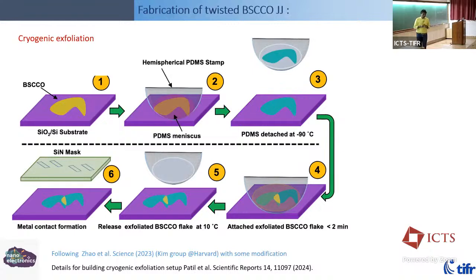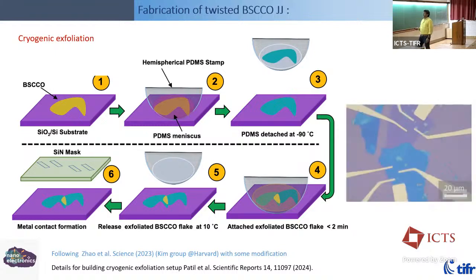So to make these devices, it's a little bit complicated. You have to peel off and exfoliate at low temperatures to make sure that the oxygen stoichiometry does not get distorted. So you take a crystal of BSCCO, exfoliate while the sample is still below -100 C inside a glove box. Within a minute or so, you twist it by whatever angle you want and you put it back. It does not like any kind of lithographic processes that people use for making electrodes. You have to make electrodes by shadow mask. If these words mean anything to you and you have questions, please talk to me at the coffee time, but some of this is technical fab-related jargon.